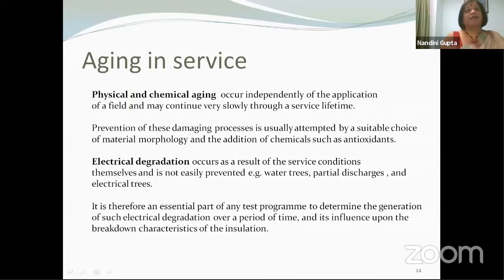What you can do is, at the instant of choosing the material, think about what kind of environment you're going to put your material in, and you can accordingly choose the material morphology. Sometimes it may be possible to add chemicals. For example, we sometimes use chemicals in order to retard trees. Tree retardant chemicals are possible. You can use antioxidants. So you can slow down the process, but you cannot prevent it. However, we are going to be more interested in the electrical degradation processes, because as I said, electrical fields exacerbate the physical and chemical processes and lead to conditions which are comparatively severe in nature.